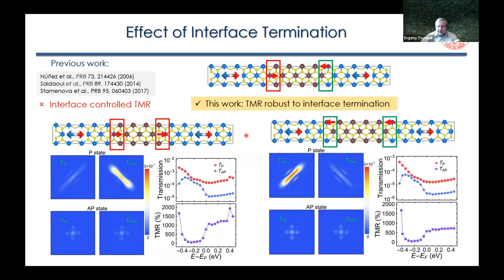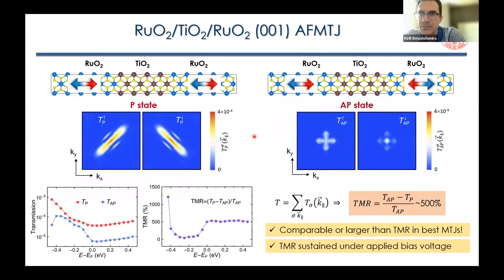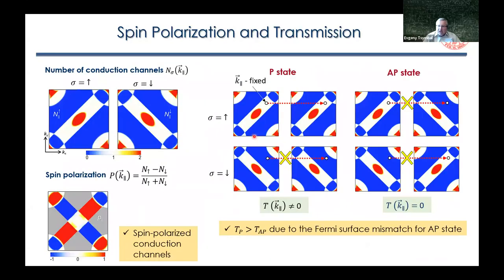The specific feature of this particular situation is that if you integrate over the whole Brillouin zone and calculate the number of conduction channels, Fermi surface integrated, you don't have any difference. So the overall conduction, for up and down spin electrons, should be the same independent of spin orientation. However, if you go to some other direction, so your transport is not parallel to magnetization but perpendicular, you will already have asymmetry in the number of conduction channels because of the asymmetry of the Fermi surface.